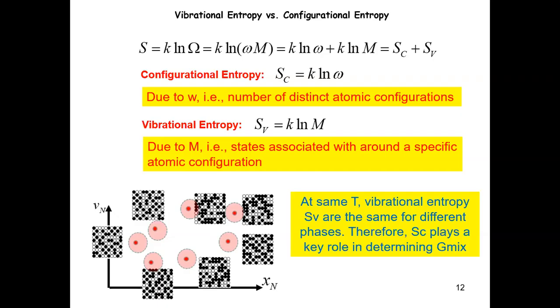So we'll take one entropy and subtract the other one, and this vibration entropy cancels one another. So we don't have to explicitly consider this part anymore. In our subsequent calculations, or subsequent counting, we just need to focus on the configurational entropy, because when you do the subtraction from one to another, we compare two different states, and the vibration entropy is going to cancel one another because they have the exact same contribution.